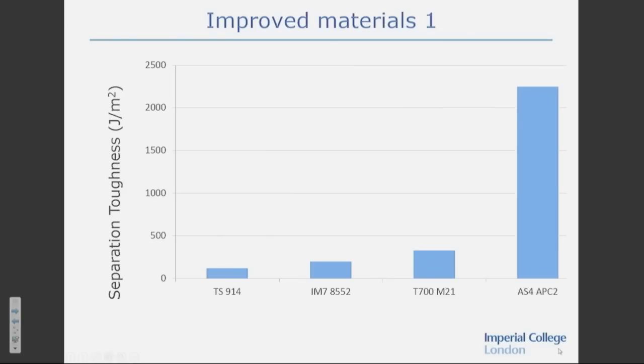If we make a switch to a different type of plastic matrix, we can get even bigger increases in toughness. So this one is a polyether ketone matrix, PEEK matrix, and it's got a toughness in the range of 2,000 joules per meter squared. So a big increase over that first generation material. So in difficult circumstances, the engineers can turn to much tougher materials.